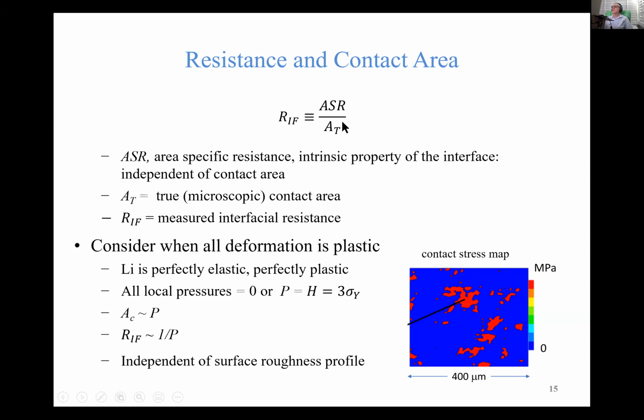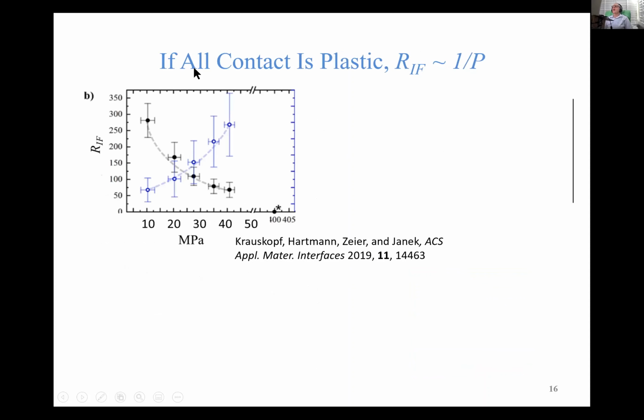So based on that, we can replace the area of contact in this equation by the pressure. And so now we conclude that the interfacial resistance has to scale like 1 over the pressure. And this is an interesting relationship. It's very general. For example, it has nothing to do with the surface roughness profile as long as all deformation is plastic. So let's see whether that actually happens. Remember, we've decided that if all contact is plastic, then the interfacial resistance should scale like 1 over the pressure.